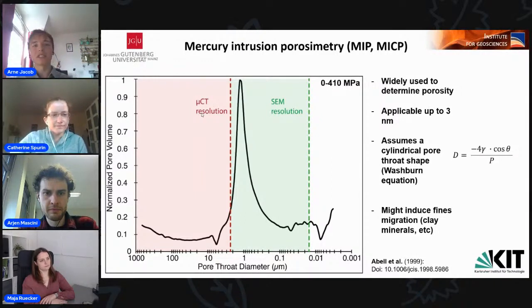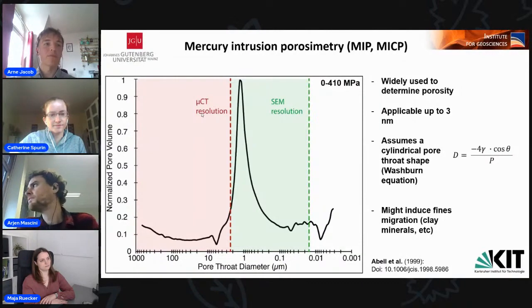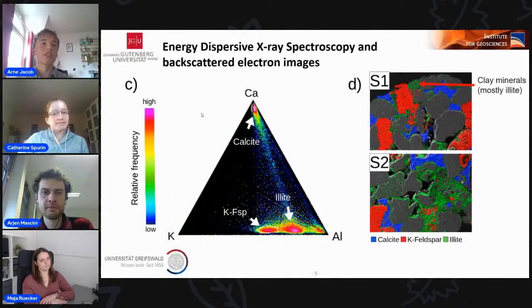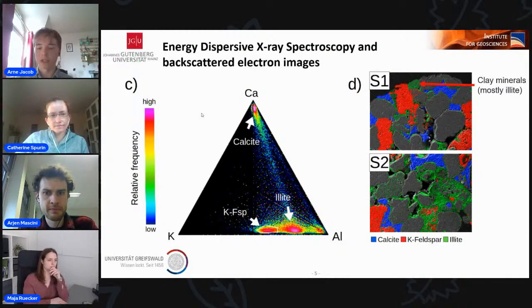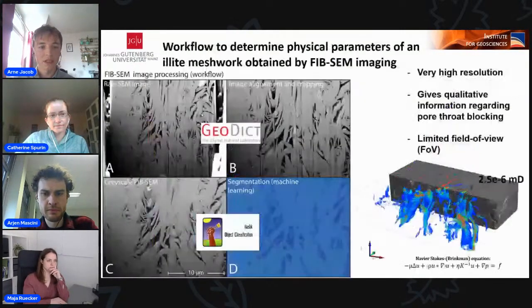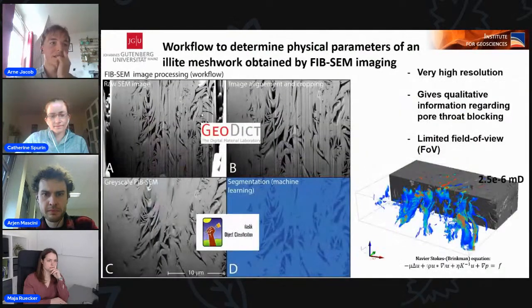And what we can see in the plot as well is that many of the pores are still below our resolution, so at 1 micrometer, while we are at 2.4 micrometers in our synchrotron scans. So in order to receive the permeability of the illite meshworks, which are hidden below our resolution, one has to post-process the data which comes out of the FIB-SEM measurements. Let me switch these slides here.